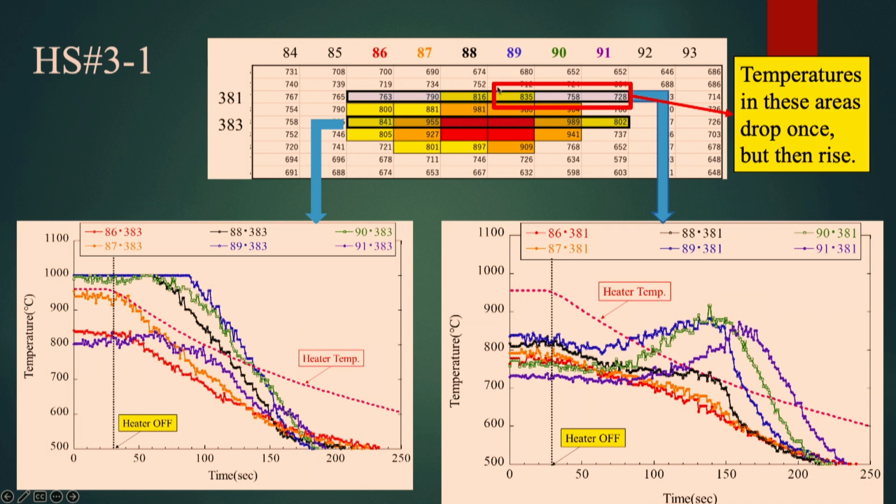And these 3 points rise. However, these 3 points decrease. If we consider this phenomenon to be induced by the hotspot heat diffusion, it cannot be explained, because these points and these points are the same distance from the hotspot region. So it's a very difficult phenomenon to understand.